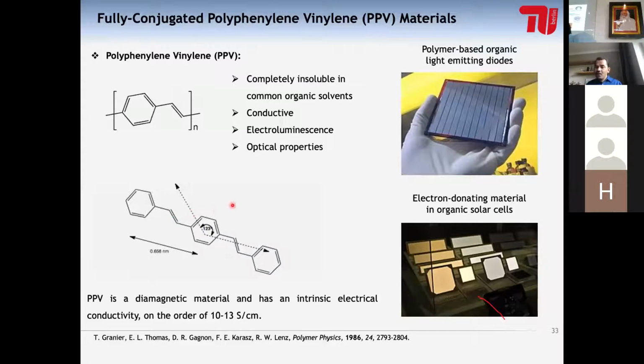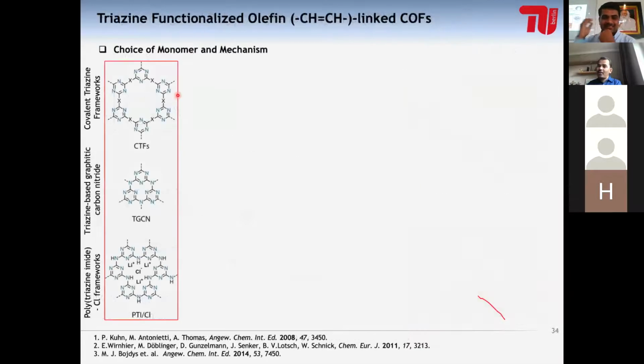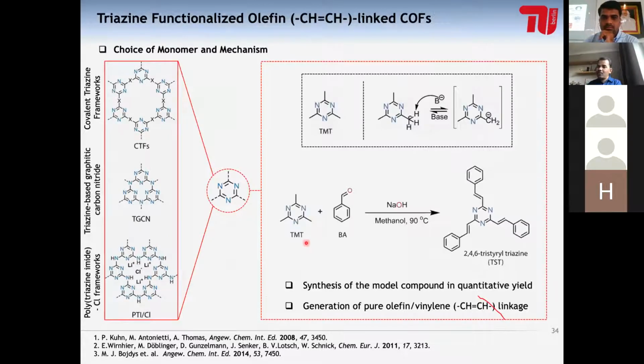So we thought it would be interesting to have materials with these symmetrical CC bonds, and we can incorporate some of the triazine moieties, which are a part of covalent triazine frameworks, carbon nitride, or some of the polyimide networks as well. And these are moieties which are really important. To incorporate that, we thought we can have a molecule, trimethyl triazine, where the nitrogen-rich, electron-poor nature of the triazine can remove electron density from here and start activating these carbon atoms.